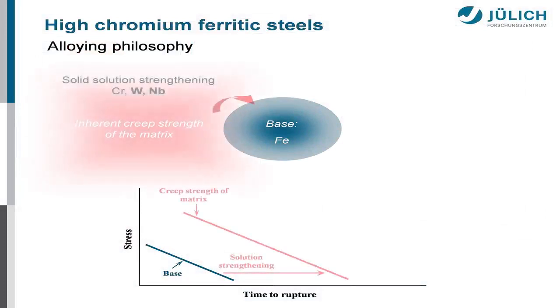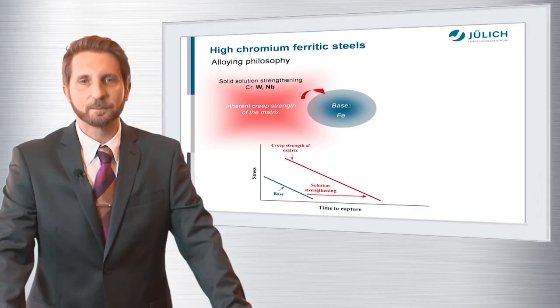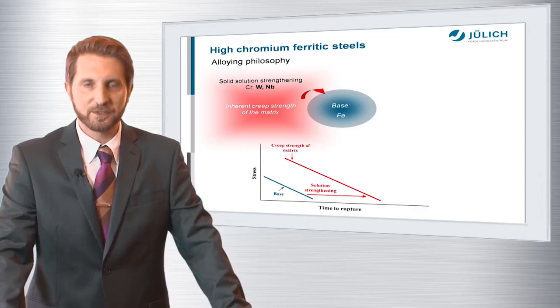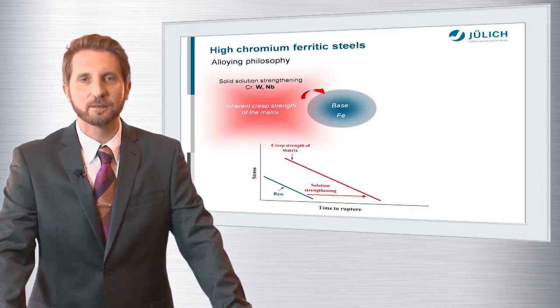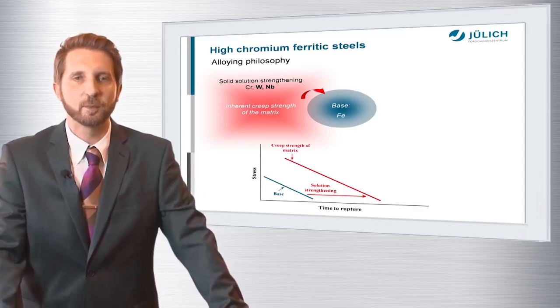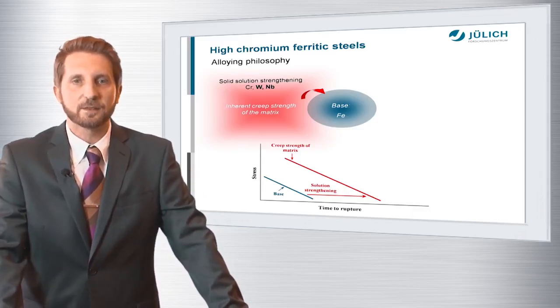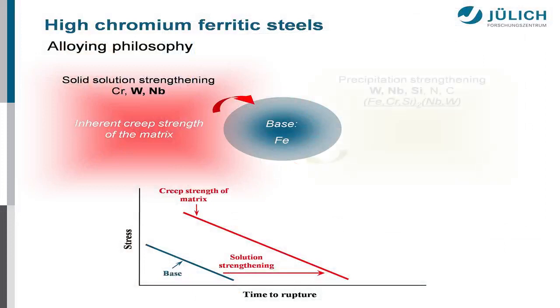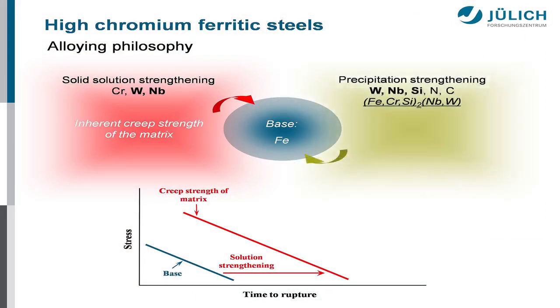high chromium ferritic steel. You start out with an iron base, you put into some solid solution strengtheners like chromium, tungsten, and niobium. Frankly speaking, chromium was included for corrosion resistance, for steam oxidation resistance, and the solid solution strengthening mainly stems from tungsten and niobium. So this solid solution strengthening gives a boost in the creep strength of the matrix, but this is still not enough. So we'll go further for precipitation strengthening.